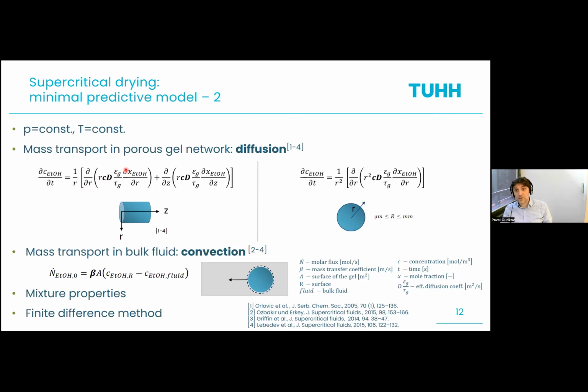Another complication is this lovely term, the porosity divided by tortuosity, that basically describes how difficult it is for me to go through the gel, because the gel is not a stationary medium. You have walls, you have to diffuse through this, and that reduces your diffusion coefficient. And if you take all this into account, you still end up with a purely diffusional approach, maybe a little bit more sophisticated. To describe a real situation, you also have to take into account convection and the mass transfer between the single particle or single cylinder and the bulk phase itself, and that is usually done with mass transfer coefficients.